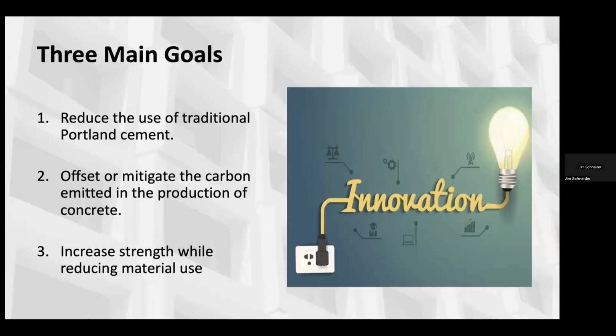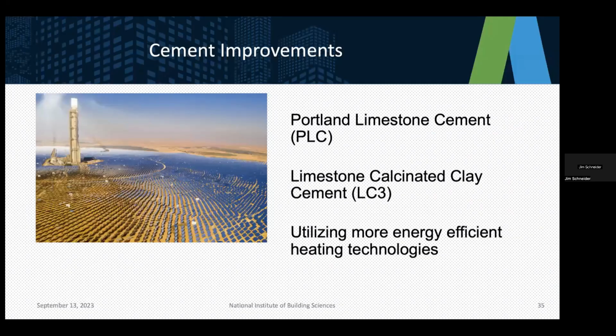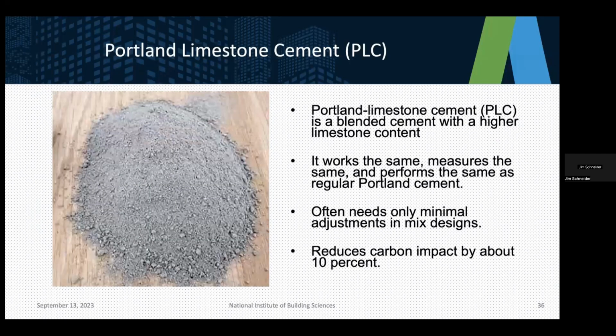That makes a big difference. So 3 main goals when we're thinking about this as an industry: we want to reduce the use of traditional Portland cement, offset or mitigate the carbon emitted in the production of concrete, which is another piece of the approach, and then also increase strength while reducing material use. So try to do more with less. So some improvements we're seeing in the world of cement, and you may have heard of some of these, are Portland limestone cement, or PLC, and limestone calcinated clay cement, or LC3. And these are cements that essentially decrease the carbon impact of cement. It's a less carbon impactful version. And also utilizing more energy efficient heating technology, which is also something we're seeing in the steel industry. So we're trying to find ways to heat these things that don't utilize so much energy.